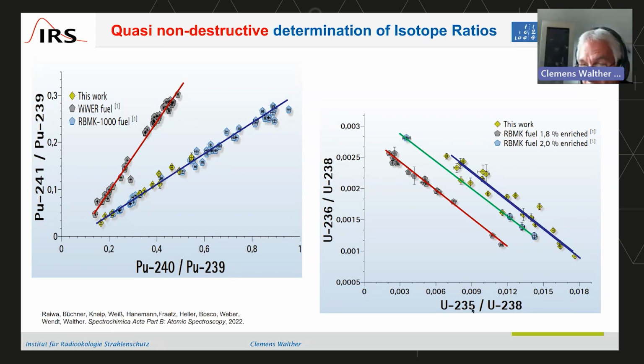We call that burn-up, because you start with a certain amount of uranium-235 in the fuel, and that is consumed by nuclear fission, and the longer it spends in the reactor, the more energy you produce, the lower the amount of uranium-235. And at the same time, you see the buildup of uranium-236. And if you compare these two isotope fractions, you can tell what kind of fuel was used in the reactor.